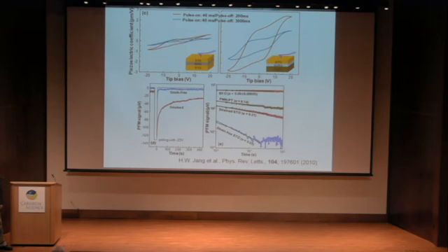However, this system relaxes so quickly when you write it by PFM that it is almost impossible to do macroscopic electrical measurements. In contrast, the strained one lasts much longer than the strain-free film.